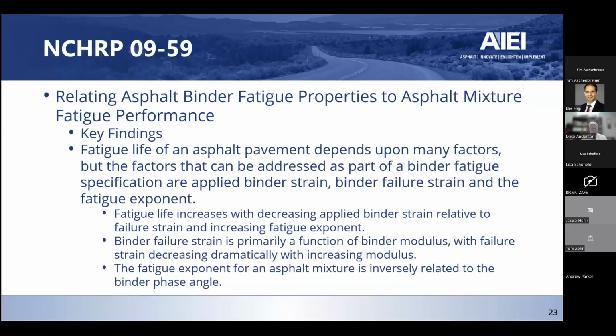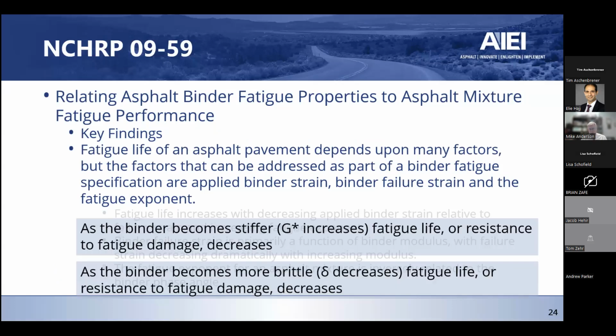Some of the key findings that they were looking at there, and I'm not going to read all this because it basically says what I've said before: fatigue life is going to depend on a lot of different things. But the focus overall is how the binder failure strain contributes and what happens to the fatigue performance. If you boil that down, as the binder becomes stiffer, as G star increases, the fatigue life or resistance to fatigue damage decreases. And as the binder becomes more brittle, as the phase angle decreases, in other words, it starts behaving more like an elastic solid than a viscous liquid, then the resistance to fatigue damage decreases. So both of those things happen, and that happens with aging.